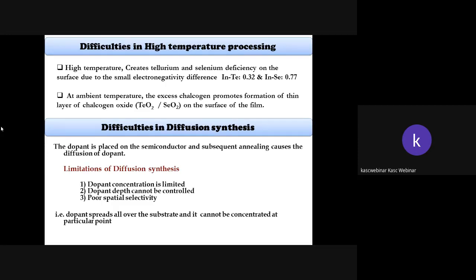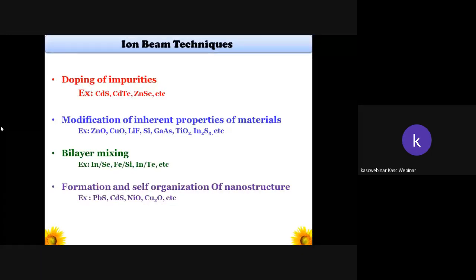Suppose you want to dope a particular material inside a metal or a sample, then we are not able to control the particular space itself. That's called poor selectivity. The dopant spreads all over the substrate, and it cannot be concentrated at an expected or particular point. So we have certain remedies for this conventional method. That's the ion beam technique. Thus, we can go for doping of impurity at a particular depth level.